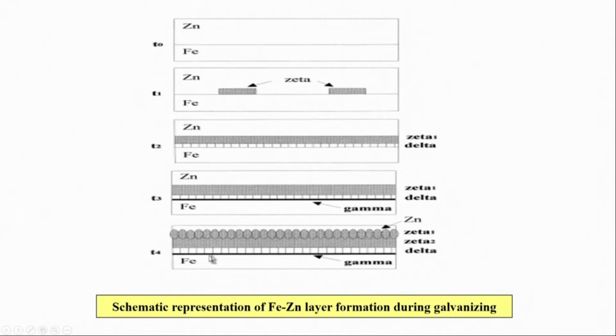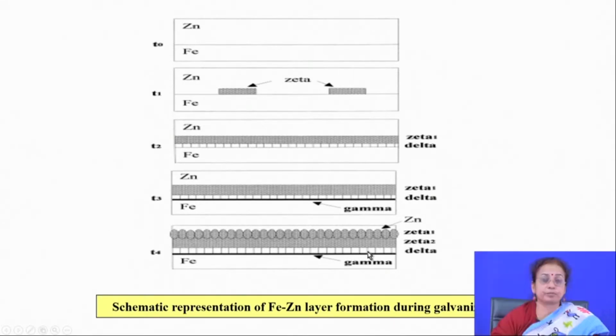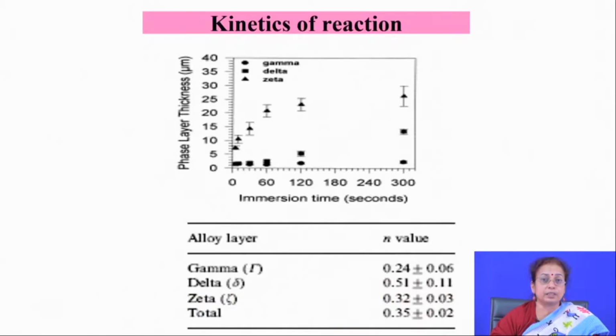So, finally, you will find the gamma phase at the interface, followed by the delta phase, then zeta 2, zeta 1, and then finally zinc with iron in solution and pure zinc. So, these are the different intermetallic phase formation sequences when you dip the iron based alloy into the molten zinc.